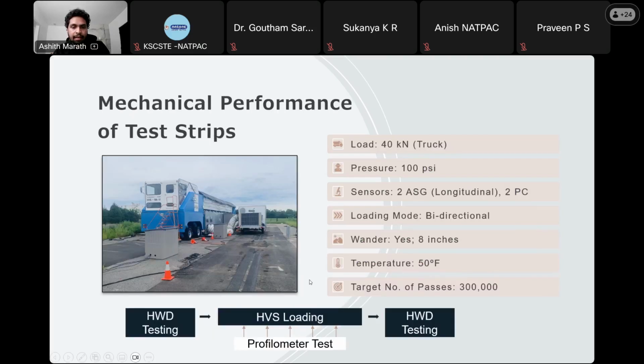With that, as we evaluated the de-icing performance of the pavements, we moved on to the mechanical performance evaluation of the test strips. There we used our HVS machine, and for loading the HVS machine, we had a target load of 40 kilonewton, which is typical for truck loading, and a tire pressure of 100 psi. We had embedded sensors in the pavement, which are asphalt strain gauges and pressure cells. It was a bi-directional loading mode, which means the load is applied in both the forward and backward direction of the wheel movement, and there was a wander applied.